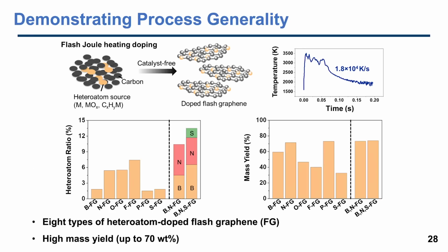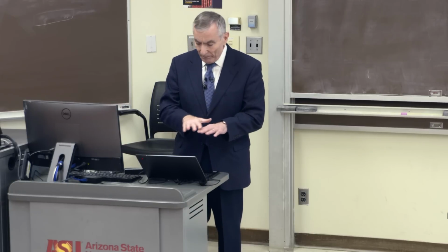So you see we can make boron-doped flash graphene, nitrogen, oxygen, fluorine, phosphorus, sulfur, or the mixed ones, for example, boron, nitrogen, sulfur, or boron, nitrogen, fluorine. The fluorine sits above and below the plane because it has a valency of 1. These other ones sit in plane, in the graphene.